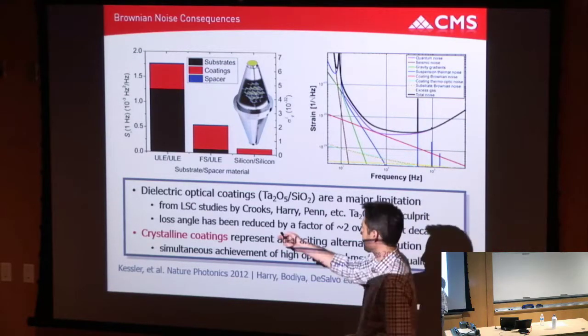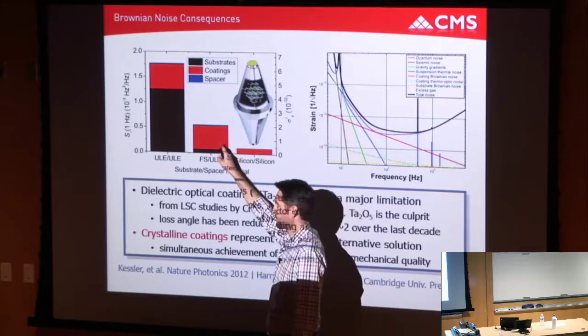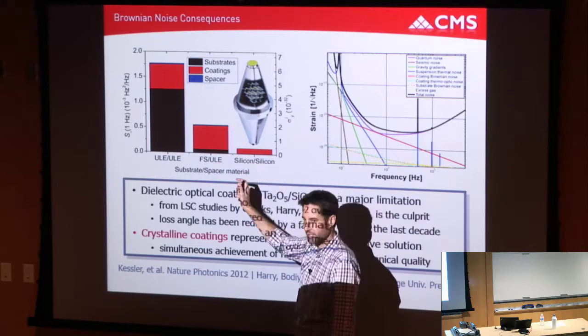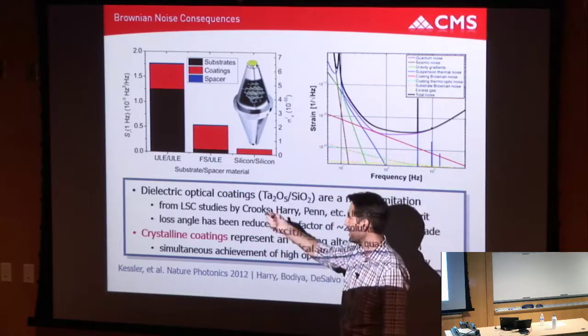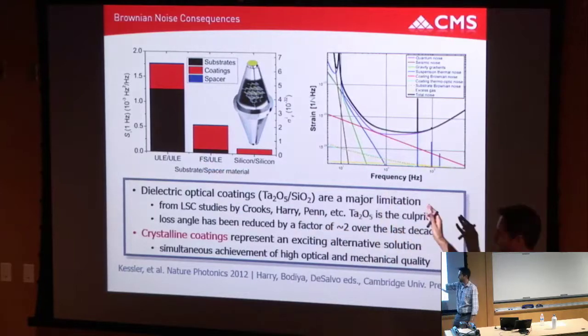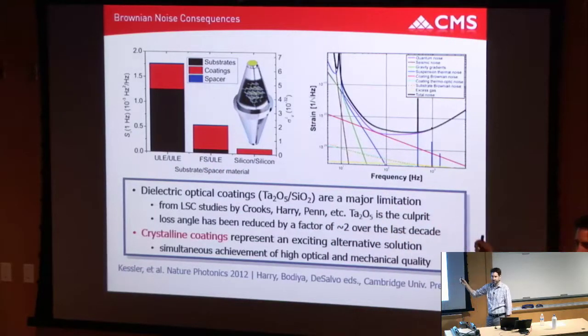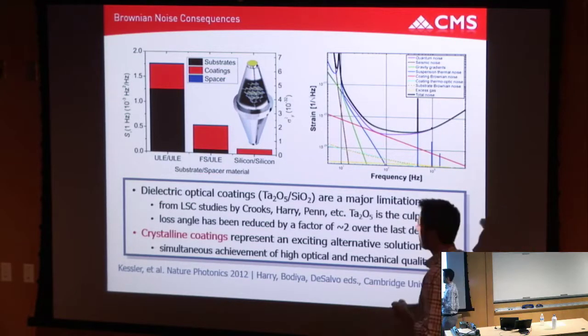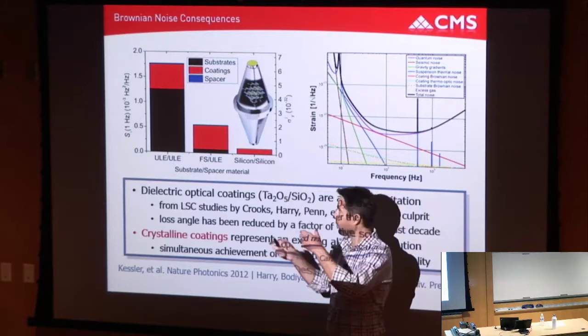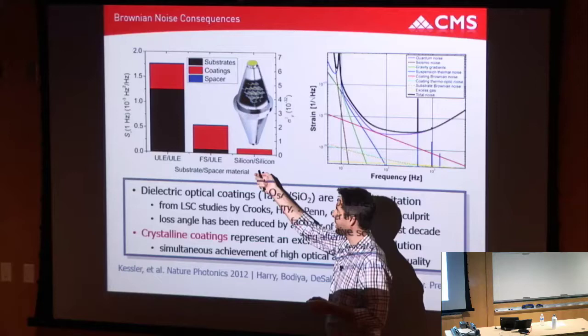And so people switched the substrates, shown in black in these bar charts, where we've color-coded the noise contribution, out to fused silica, which has a much higher quality factor. And you can see the noise from the substrate drops significantly. And in this plot, all of the coatings are standard ion beam sputtered coatings. These two systems are at room temperature, and this last system is at cryogenic temperature. So in this all-silicon cavity, you have ultra-high Q for both the whole big 21-centimeter bulk piece of single crystal silicon that sits at cryogenic temperatures and the single crystal silicon substrates.